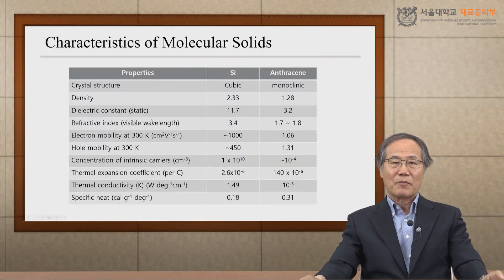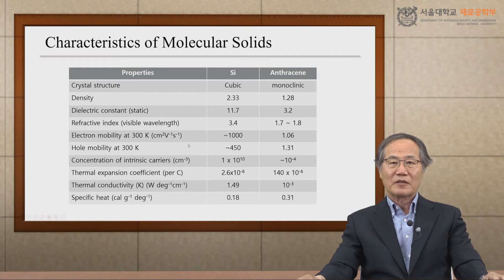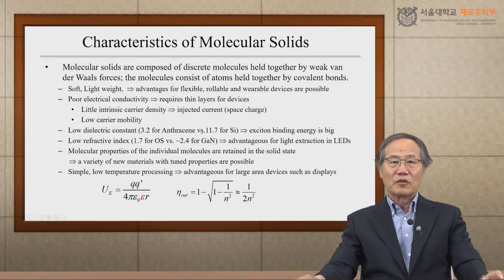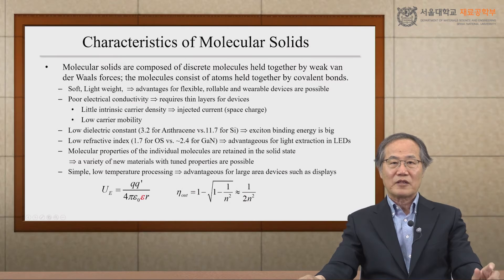These properties are compared in this table. The electron mobility for silicon is about 1,000 cm²/V·s, but for an anthracene crystal — even for the crystal case — it is about 1 cm²/V·s. So the mobility is low. The intrinsic carrier density is about 10¹⁰ for silicon, but for anthracene it is negligible — which means poor conductivity. We can overcome this poor conductivity disadvantage by using thin nanometer-thick layers.